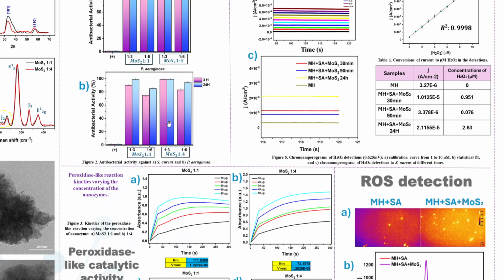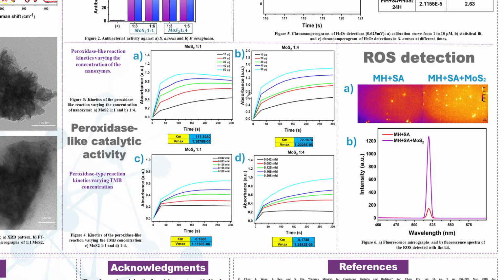We investigated the peroxidase activity of the nanozyme. As shown in the kinetic curves, the oxidation of TMB strongly depends on the concentration of the molybdenum disulfide nanozymes. As the amount of nanozyme increases, we observe progressively higher absorbance, indicating increased formation of oxidized TMB. We also evaluated the effect of TMB and hydrogen peroxide concentration on the catalytic response. The results confirm that our molybdenum disulfide materials exhibit intrinsic peroxidase-like behavior in the presence of hydrogen peroxide.